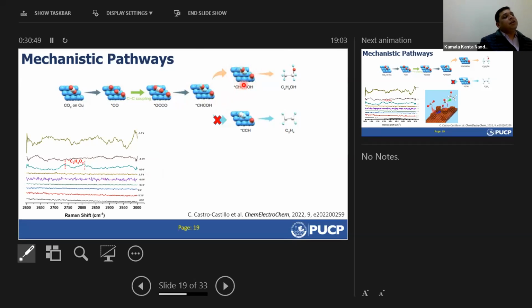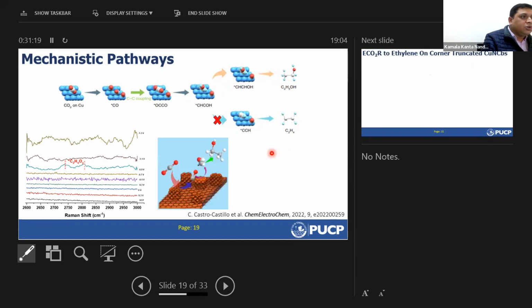So we concluded that the presence of graphene or reduced graphene oxide on the surface of the electrode is driving the last step of this reaction towards ethanol, and we are not getting this kind of intermediate, so ethylene production, or we are getting less of this intermediate, so that ethylene formation is hampered. So by applying this process, we can scale up to the industrial current density to obtain selectively ethanol from CO2 electroreduction. And this is the mechanism that I was talking about.